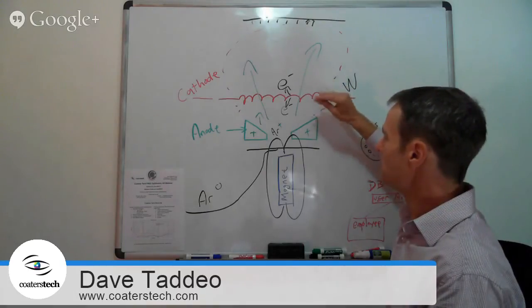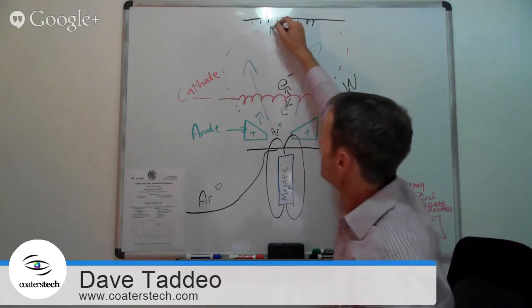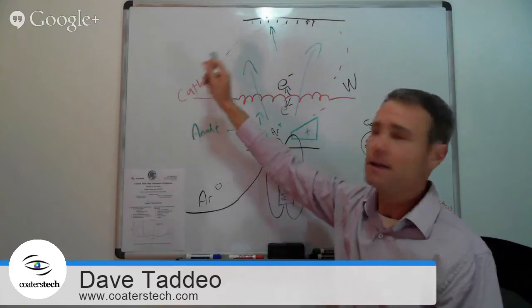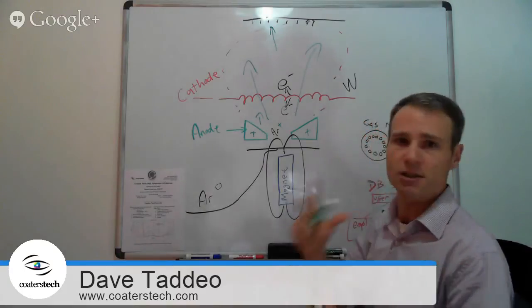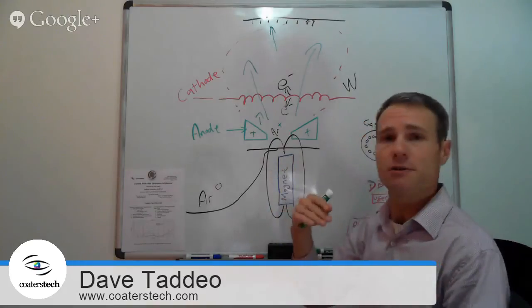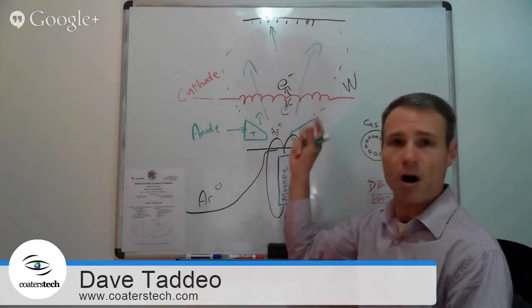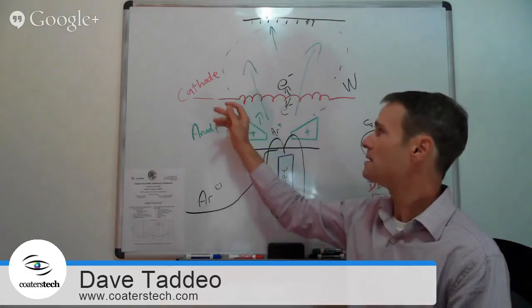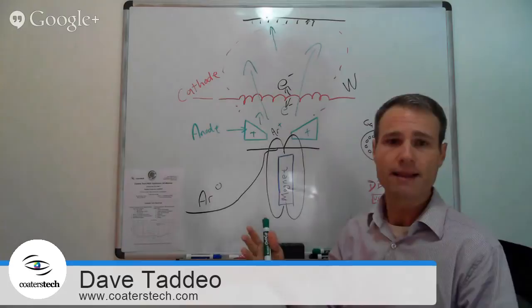The cathode will neutralize some of that charge so that the argon ions making contact with our lenses and the metal tooling don't create a discharge. We don't get that charge buildup and sparking. Sometimes you can see arcing and sparking when you look in the coating chamber. If you do see that, you can adjust your neutralization current to bring that down or eliminate it completely.